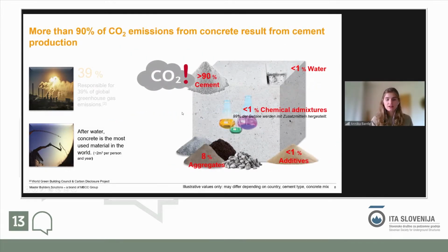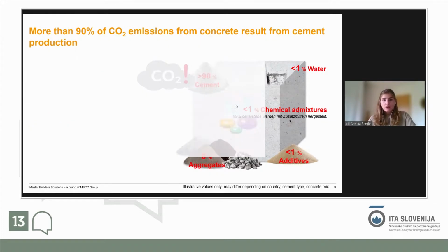And if we have a look, not just remembering cement being 8 to 15% of the mass, but looking at the CO2 emissions that result from these components in the concrete, cement is responsible for over 90% of all CO2 emissions stored in or resulting from a cubic meter of concrete. Water is just below 1%, chemical admixtures as well, and additives and aggregates are responsible for around 8% of the CO2 emissions. But yes, you can see here, cement is really the thing we should be looking at, which is why we're doing it now.